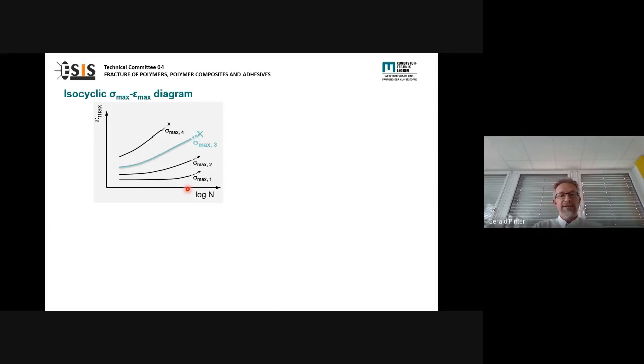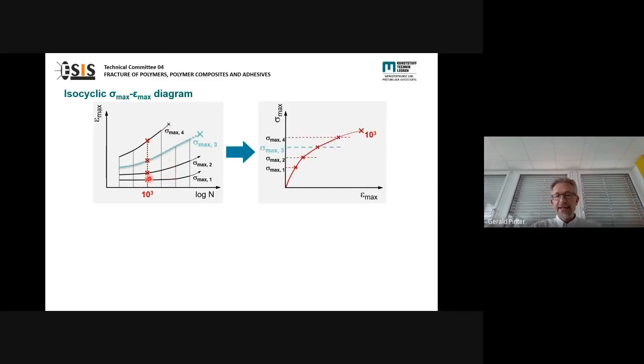And then what we are interested in now is the situation after defined cycle numbers. So, for example, after 1000 cycles. In order to transform this information, we transform it into a sigma max epsilon max diagram. So these 4 points are transformed into this new diagram at the four different stress levels. And what we get then is a so-called isocyclic stress strain diagram. That means now we really have the stress strain behavior of the material after a defined cycle number. And then we can do this at different cycle numbers.